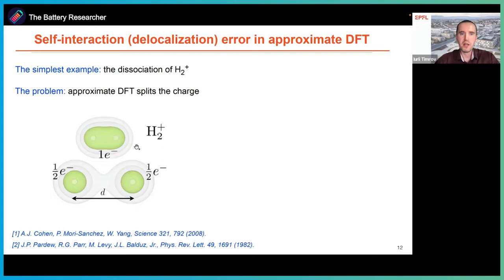If we use DFT, what we obtain is that the charge density is distributed equally between the left ion and right ion. So we have 50% on the left and 50% on the right. But we know that if we solve the Schrodinger equation for this system, there are actually many solutions. What we show here is one solution, but there can be others. For example, we can have 100% of the electron on the left and zero on the right, or vice versa, 100% on the right, zero on the left, or any linear combination of these is also a good solution, like 75% on the left and 25% on the right, etc. But DFT gives us just one solution, 50-50.